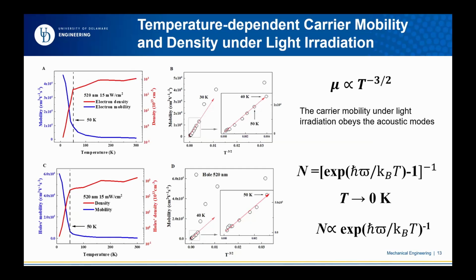And here, that's mobility, as I mentioned. You increase it a lot, and also the charge density. Here the charges are not just thermally generated; they are photo-generated charges. Photo-generated charges are totally different from thermally generated ones. That is a big difference, because it can avoid the so-called freezing effect.